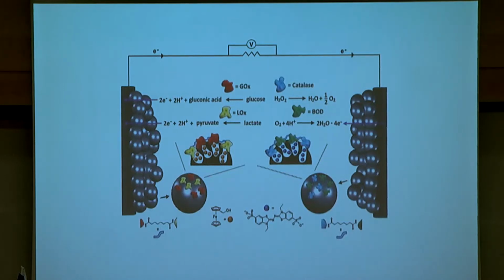And in fact, about 10 years before we did this system, I think that we were the first to generate a biofuel cell that was very inefficient, but it demonstrated the feasibility of a biofuel cell. But once we had this system of porous carbon nanoparticles, we were able to construct a biofuel cell that demonstrates substantially higher activity. And what we did is, as an anode, we used electrically contacted porous carbon nanoparticles that included the ferrocene as an electron mediator, and this system was loaded with either lactate oxidase or glucose oxidase as the bioelectrocatalytic active enzyme.